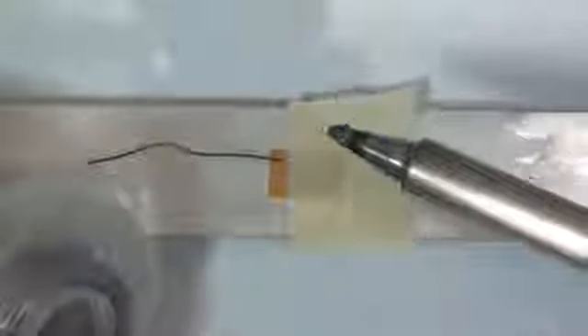So we are going to use this. You're going to tin the tabs first? We can tin the tabs first. So we put the tip of the solder in the middle of the square. Have a pool of fresh solder on the tip of the soldering pencil, and then press down with the pencil on the solder and on the strain gauge tab. Then lift the pencil and the solder off at the same time. Repeat this process on the other tab of the strain gauge. And if the tinning is not satisfactory, then the process can be repeated on the tabs until we are sure that the tinning has taken place.